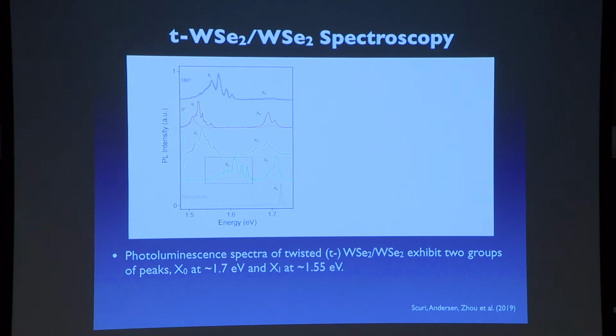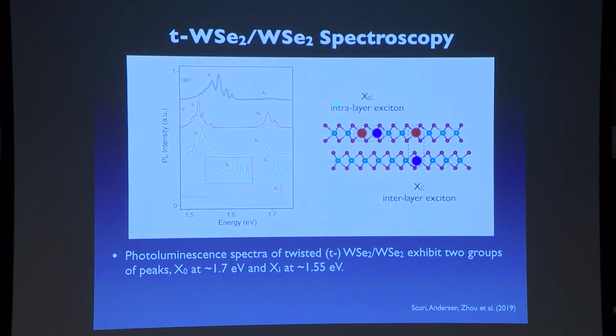The first thing that we did was to characterize a spectrum of these twisted tungsten diselenide bilayers. So starting from monolayers and then adding another layer, it turns out that 180-degree angle is what happens when you have so-called naturally stacked bilayers. So this is naturally stacked bilayers. We flipped one of the layers over and then made a 0-degree angle, 2-degree angle, 17-degree angle, and measured the spectrum. One thing that you notice is that there are two groups of peaks, noted as X0 and Xi. What are they coming from? Well, they come from two different kinds of excitons. One exciton is coming from so-called intra-layer excitons, where electrons and holes are residing in the same layer. The other one is coming from so-called interlayer excitons, where electrons and holes are separated into separate layers.